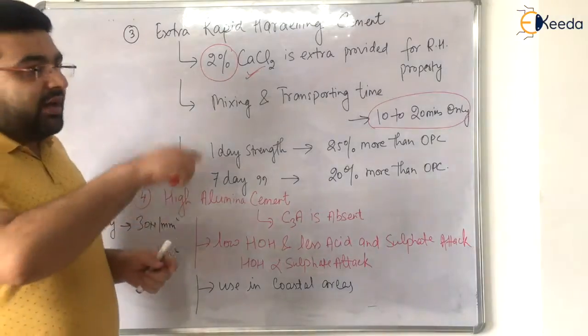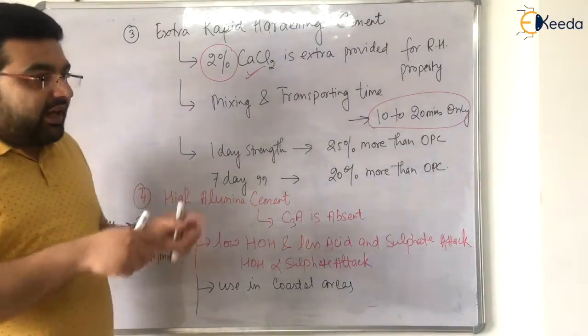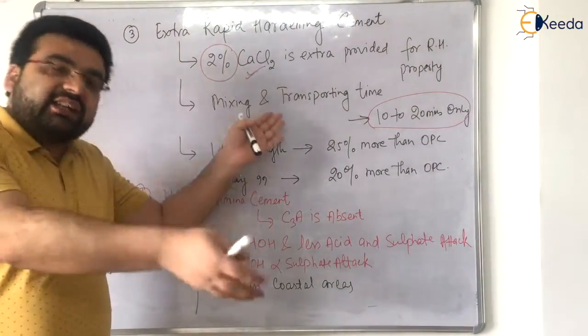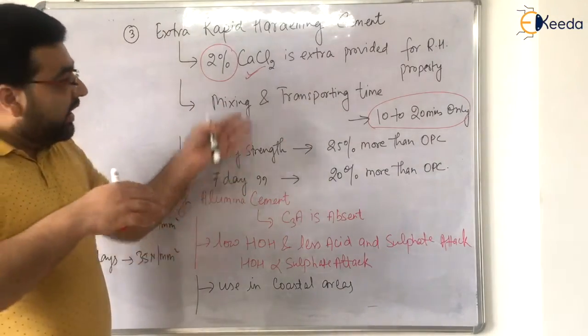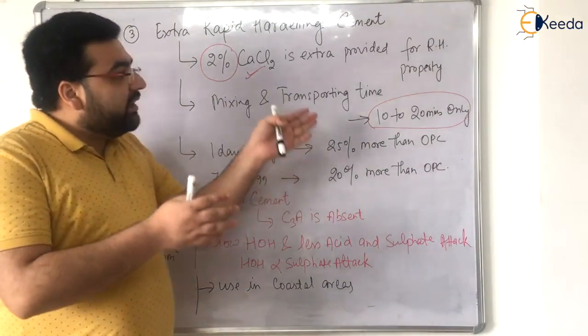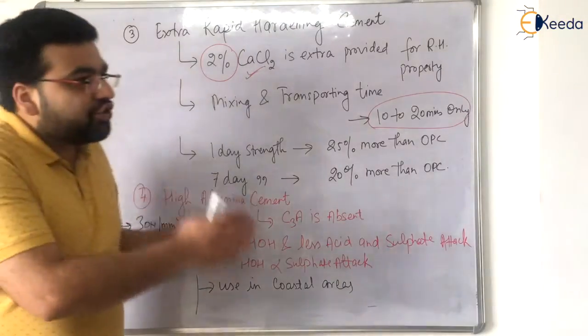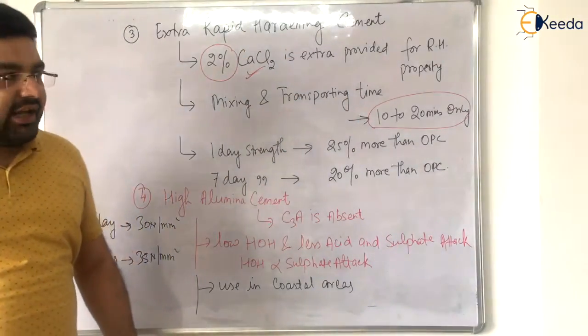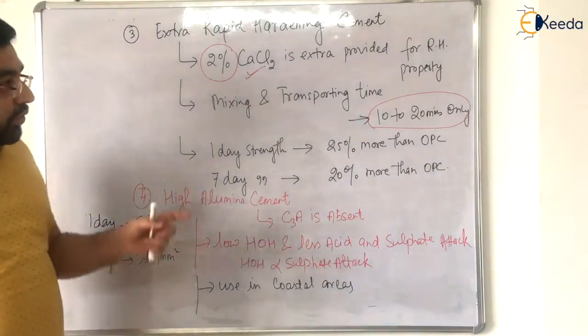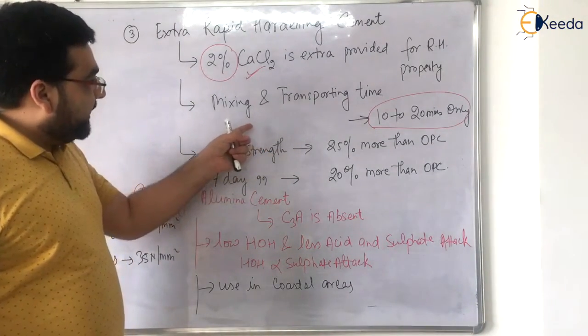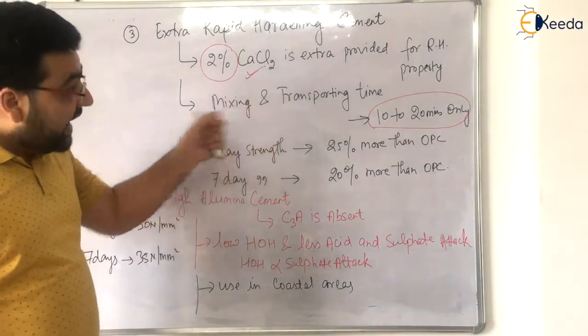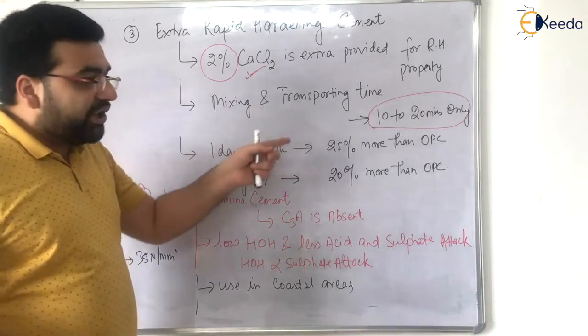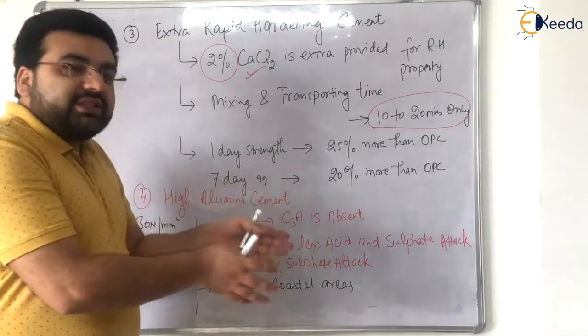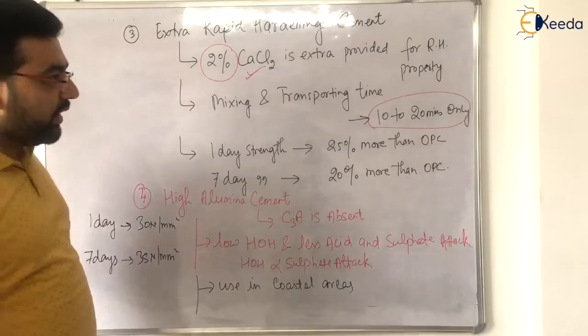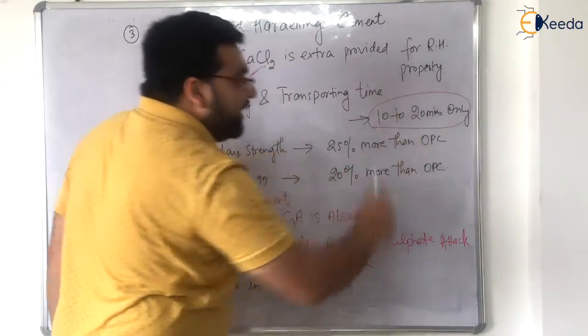Otherwise, what will happen? In the batch mixers, the cement will set in the batches itself, right? So it will be almost next to impossible to transport it to a larger distance. So this is a con, that the mixing and transportation site should be very close to the actual application site, because the time is very small, 10 to 20 minutes only.